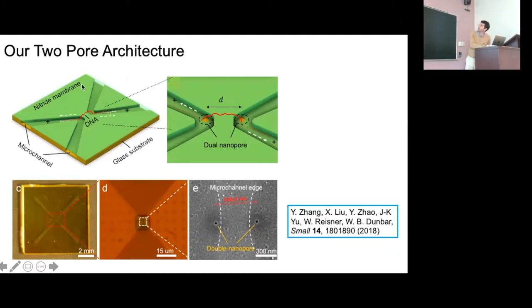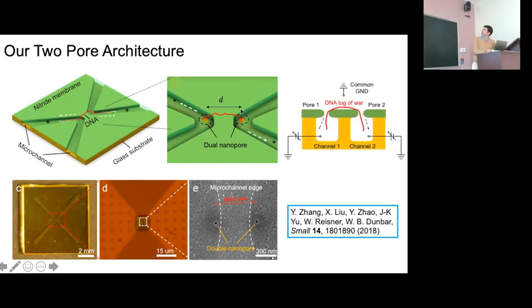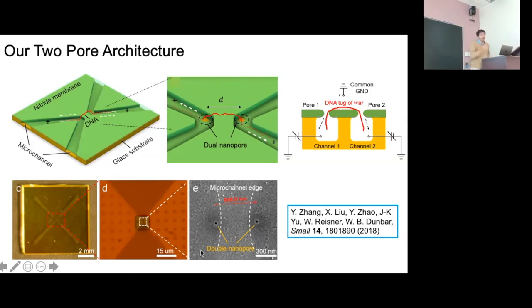The dual-pore architecture we developed is based on a wafer-scale approach. We have micro-channels etched in borosilicate glass, then bond a wafer with a silicon nitride membrane to that wafer, remove the borosilicate, and punch pores at the apex of these two micro-channels. We put a PDMS reservoir over that. Overall you have a system of two reservoirs with the DNA dangling between the pores. This is the connection between our pore fabrication approach and this application — this is why it's interesting to make more than one pore.